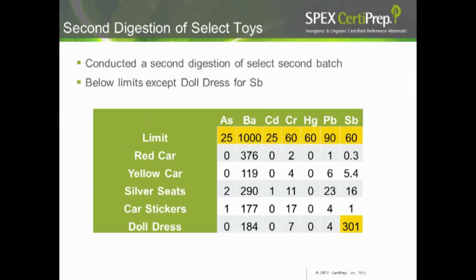Now with 2 studies under our belt, we said, okay, let's do a follow-up, and we'll do a second digestion of some of the more interesting toys from the first 2 runs. And we did our cars, we did our doll's dress, and a few of the other items. What we did find is when we did the second digestion, those barium levels did fall below the limits, but the antimony level in that doll's dress went way up. So the antimony was there in the sample, but was not actually migrating into the extraction. So the antimony in the doll's dress was 301.